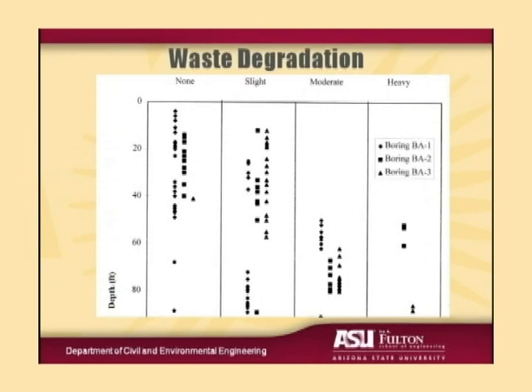What we also encountered, and that's reflected in the scattered nature of this plot, was that the waste was very cellular. We would hit pockets of standing water at shallow depth. We would punch through those pockets, and then we would encounter a dry zone with relatively undisturbed waste. So a very inhomogeneous character to the waste in the landfill.